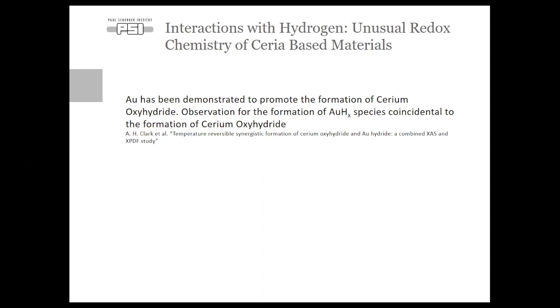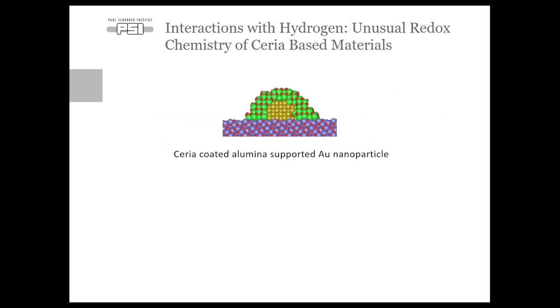So, speaking of hydrochlorination reactions, I have a second example here, which is of gold, a very complex gold structure. So, this was a cerium-coated, alumina-supported material, and we were looking at how this material interacts with hydrogen. So, this was the rough kind of structural material. We have an alumina support, and then we have a supported gold nanoparticle, and on top of that, we are coating that gold nanoparticle with a thin layer of cerium. So, gold cerium materials have actually recently been found to be very active in hydrochlorination reactions of, for instance, acetylene. Now, this is quite interesting industrially, because it provides a very nice way of producing very high-grade vinyl chlorides. But the reason for this reactivity is little understood to date.